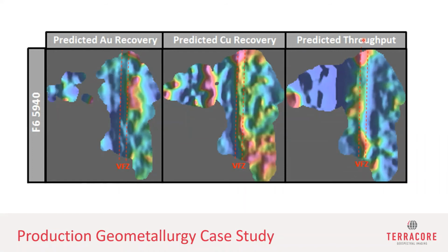They knew that when they're in this fault zone, as an example, they get very high throughputs, and there's a simple reason for that, it's mica-rich. But they also knew that their gold recovery was disgusting, and there's a good reason for that, it's mica-rich. Copper recoveries were variable. Out to the west here, they've got a thermally altered granite where they know they get fantastically good copper recoveries, but they get very low throughputs. So everything matches very nicely to what they know about the operation.